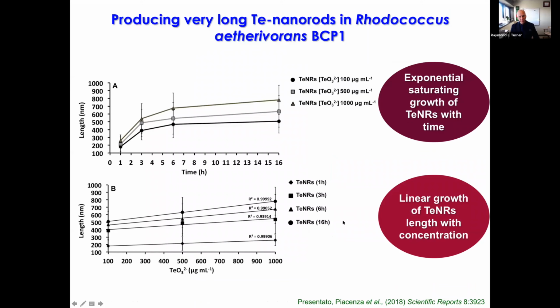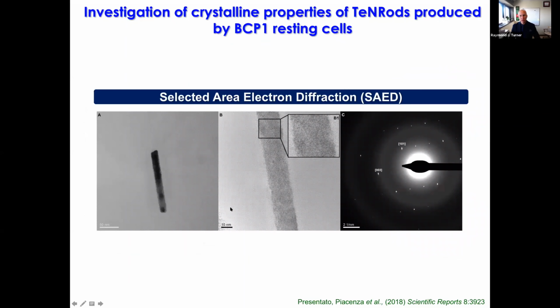But it follows fairly nice kinetics relationships to length for the concentration and the time of incubation, so that we now know we can predict. If we want 700 nanometer rods, we can choose the conditions quite nicely. It's a very nice relationship here.